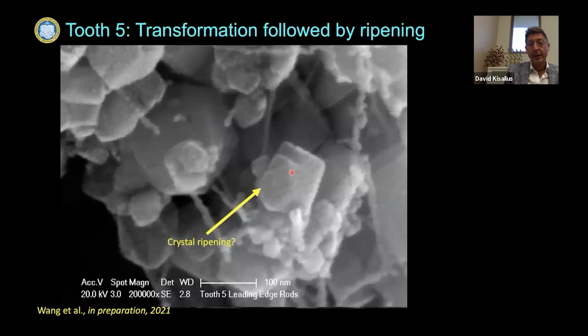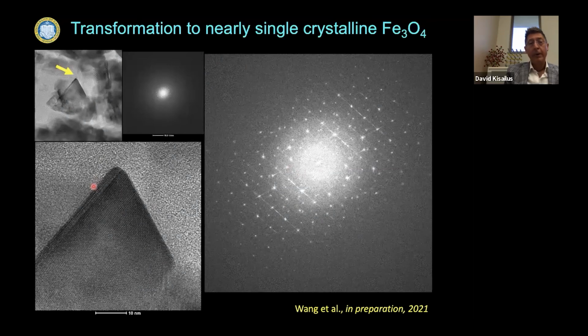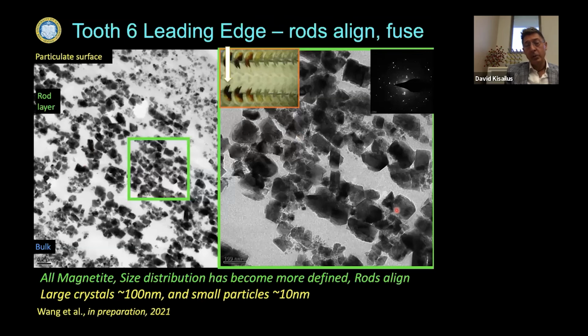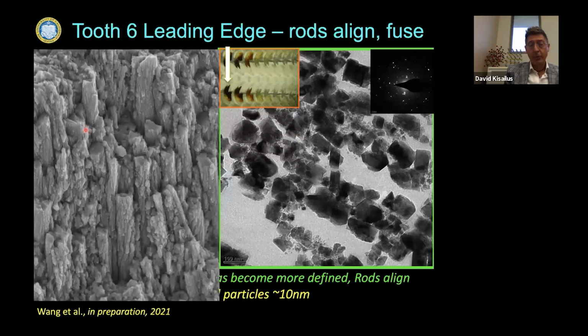So this is just an SEM showing where the mesocrystalline part of the particle is. You can see this top part of the particle that looks quite smooth and faceted, and we can see that even more in this TEM micrograph. There's Ostwald ripening of these minerals that occurs that eventually will yield continuous nanorods that we see in the fully mineralized teeth.